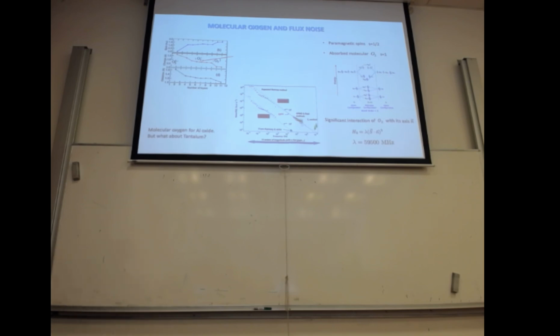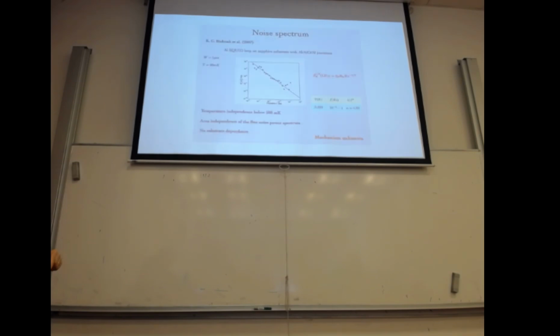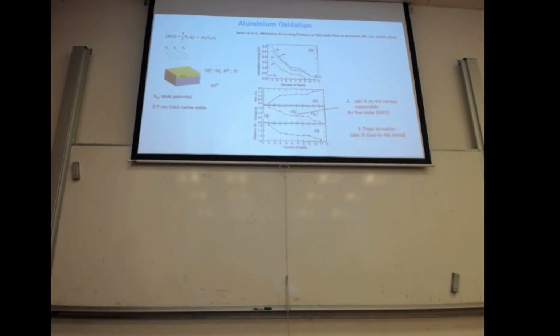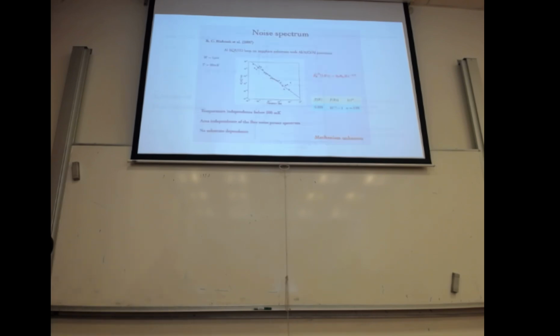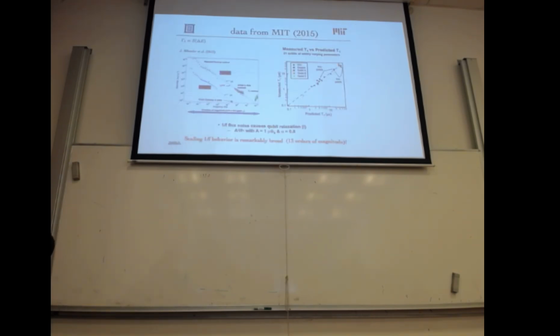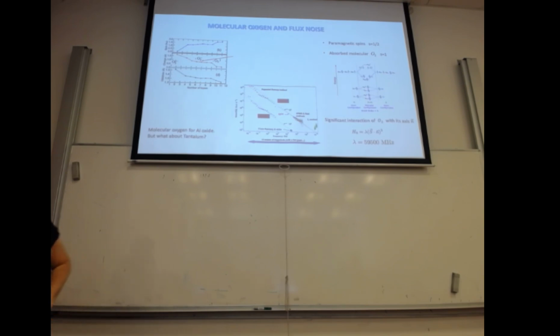And then come the other things that we saw, right? Because what you see is that very close to the aluminium you have this O2 minus, but outside, a little bit in the other layer, you have O2. So with the aluminium you remain with molecular oxygen. And this changed the game a lot, because it means that this flux noise is indeed due to two kinds of spins. There are paramagnetic spins 1/2, but there are also adsorbed molecular O2, and these carry a triplet spin.